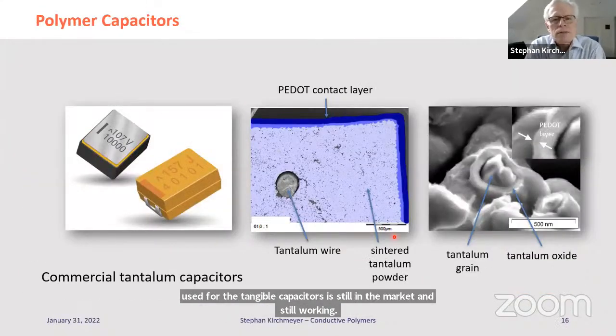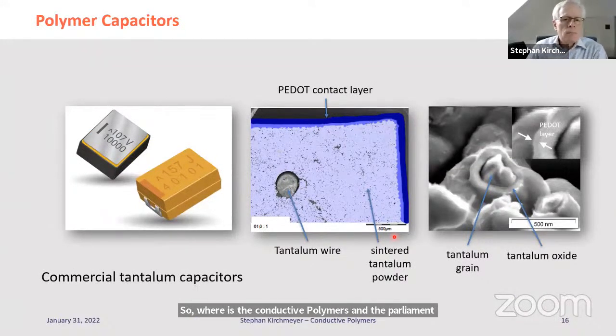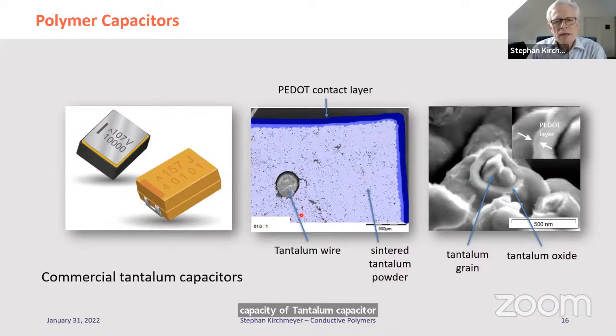So where are the conductive polymers and the polymer caps? Such a polymer cap could, for example, look like this. This is an SMT type, a surface-mounted type of tantalum capacitor. It has the tantalum powder inside. The inside is impregnated with the PEDOT and has an outer shell of PEDOT, which then acts as the counter electrode. The counter electrode is then connected to one of these.